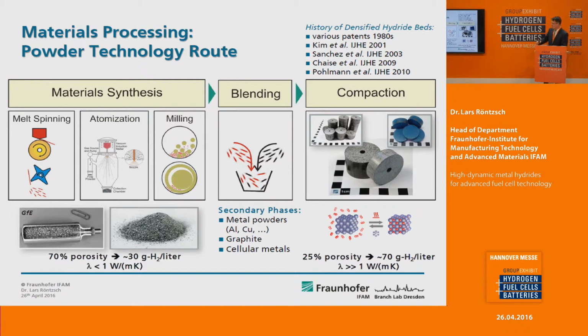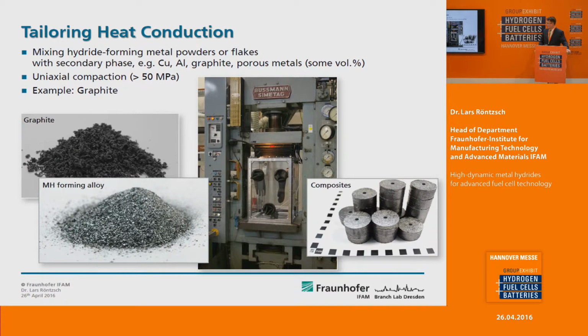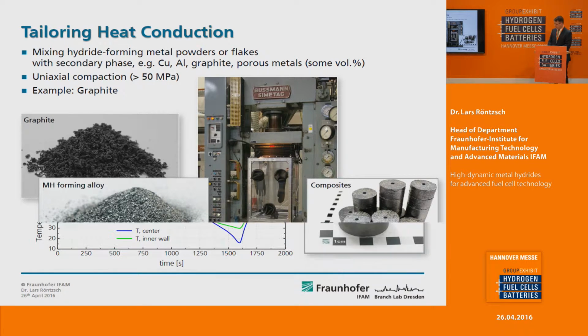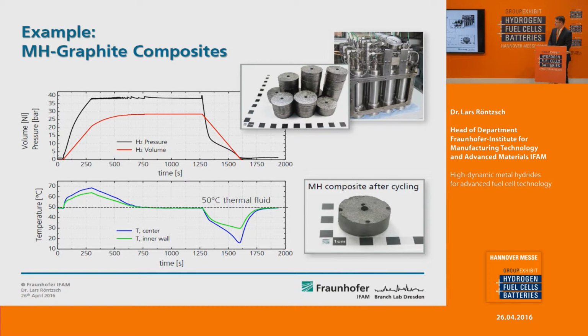And the numbers on the right-hand side explain that we can reach much higher heat conductivity and, of course, decrease the porosity of the storage bed by the compaction step. This is how it looks like in a pre-industrial scale. So you have different powders, you mix them, and then you compact these tablet forms.